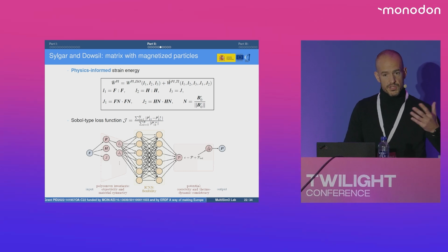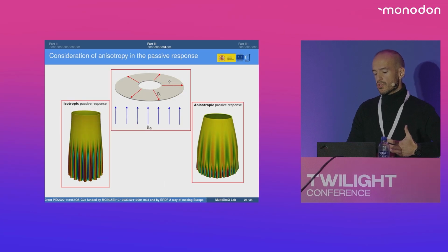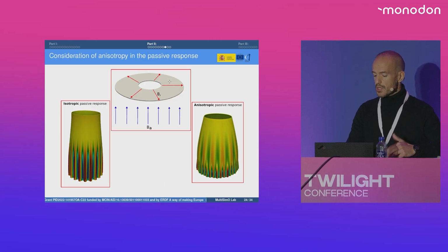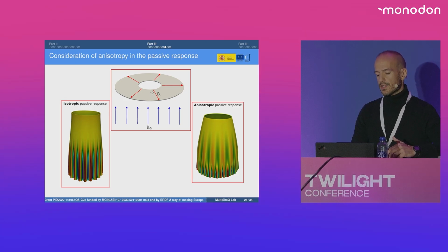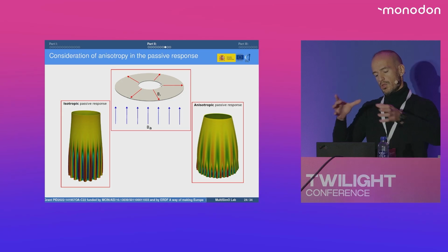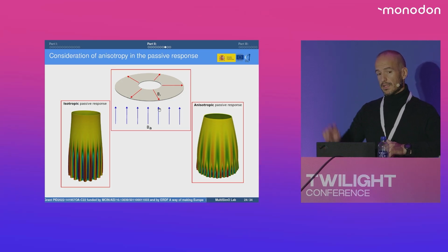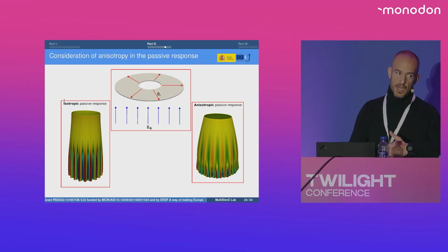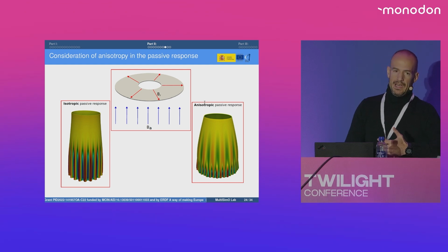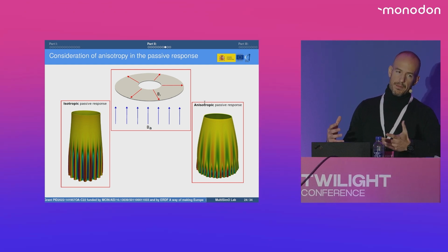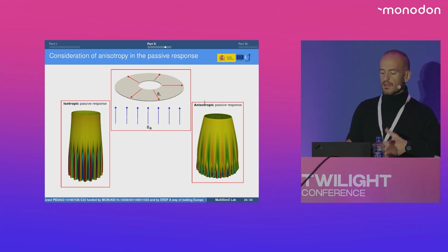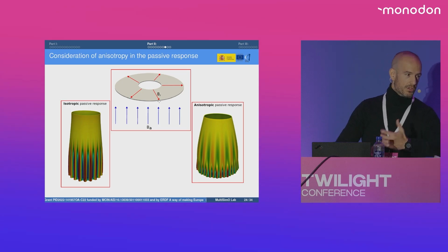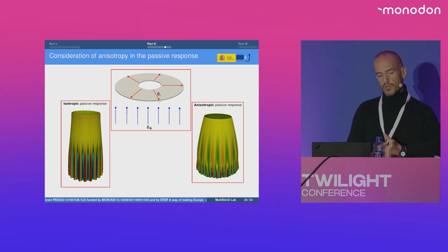They prove that the effect of anisotropy is important in the lab, and we also demonstrated that in simulations. For instance, you have a simulation here where you pre-magnetize the particles in a radial direction. You fix the inner radius, and then you apply a magnetic field downwards. There is a mistake here. This is downwards. Okay? And then what happens is that if you consider the passive response being isotropic or being anisotropic, to a certain extent, the responses of both can be qualitatively similar, okay? But in this particular example, there was a point beyond which wrinkles started to appear. And then you can see clearly that the wrinkling pattern exhibited by considering or neglecting the anisotropic contribution was actually quite different.